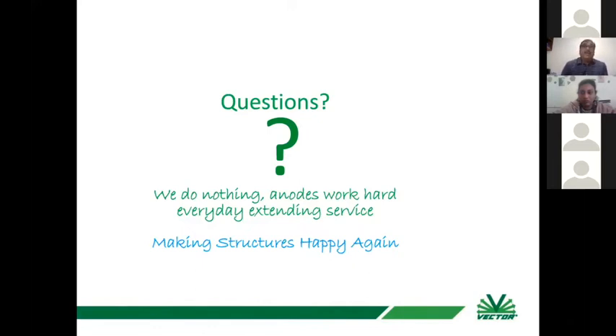In that case, if it is a medium-sized column of 600 by 600 mm or so, you can simply tie one anode at that interface and do whatever you want to do. That's all. This anode will protect against corrosion. It will corrode itself and will not allow corrosion of the rebar in the concrete. That will be a great help to everybody. It will not cost much.